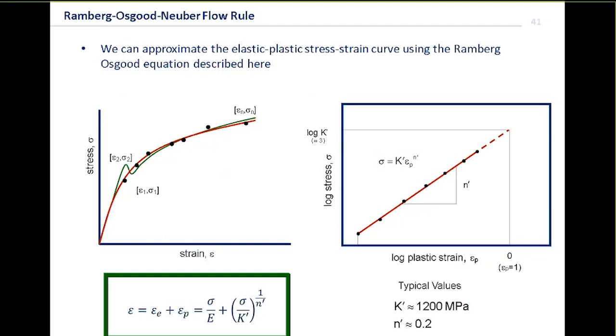And the equation is simply, we know in the elastic regime that the elastic strain is simply the stress over the modulus of elasticity. So what we do is we add a plastic component to that as well. That one we model as stress divided by K prime raised to the power of 1 over N prime. So you can see what we've done. We've fit a straight line in log space through that. And we see that in that right-hand plot.